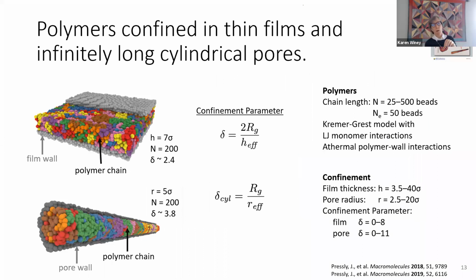So we're confining polymers with infinitely long cylinders or infinitely wide thin films. In these particular simulations, the gray beads are the rigid wall. We're not using a flat wall, we're using a wall that's made out of glassy beads, and this is to prevent crystallization at the smooth surfaces. We're defining a confinement parameter, which is 2Rg, the length scale of the polymer, so that'll depend on molecular weight, divided by the thickness of the film.